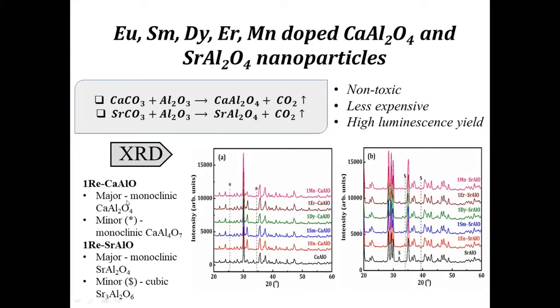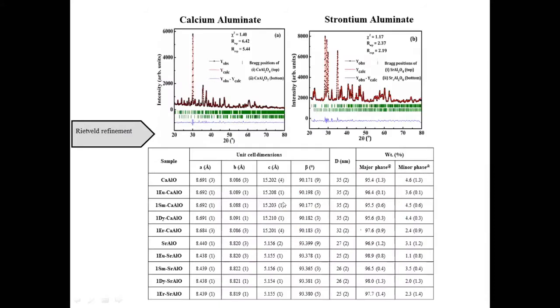And we get mostly the monoclinic CaAl2O4 phase, and a very small concentration of CaAl4O7 phase is also seen, and that we confirm by X-ray diffraction measurements. And we do Rietveld analysis. So we see the formation of